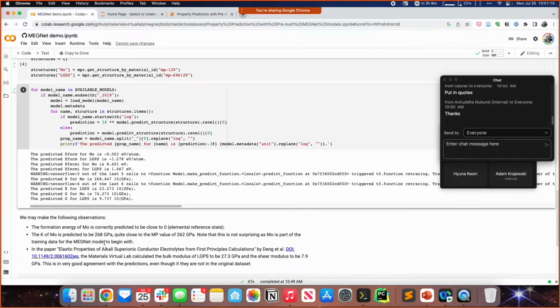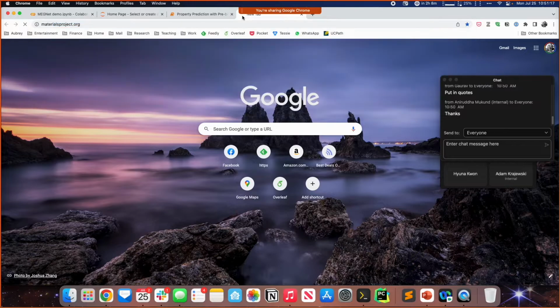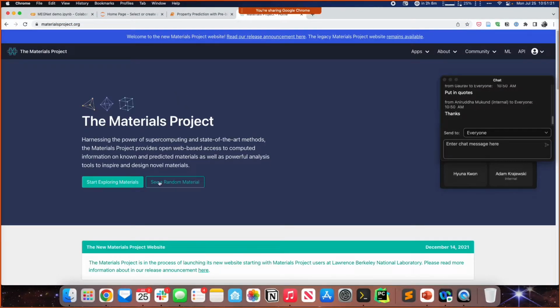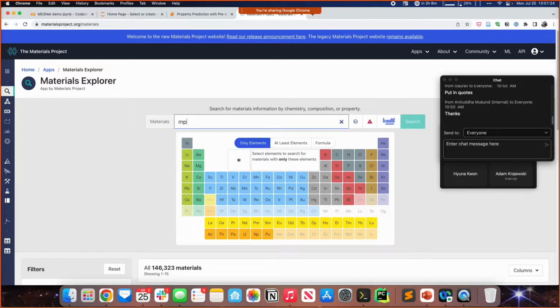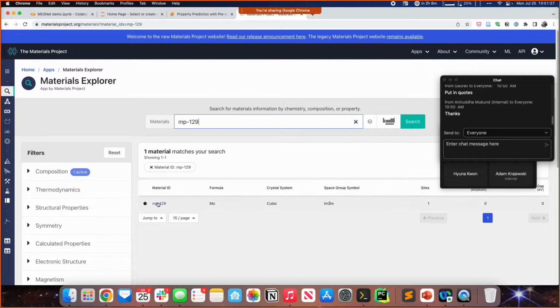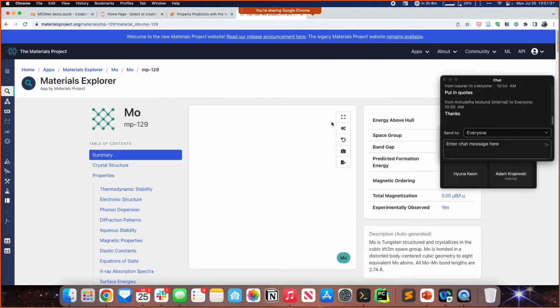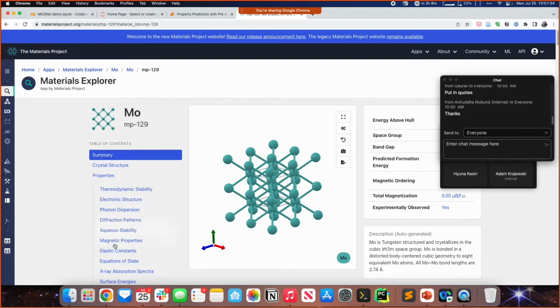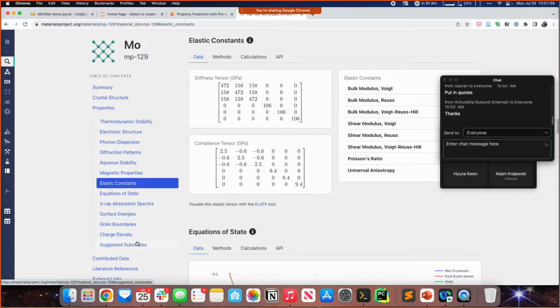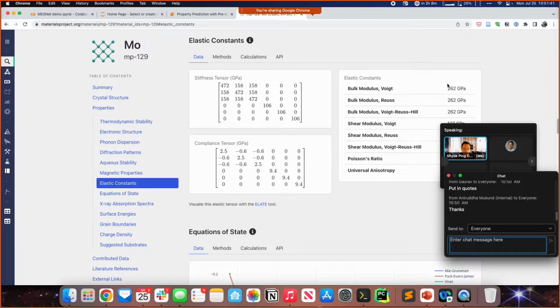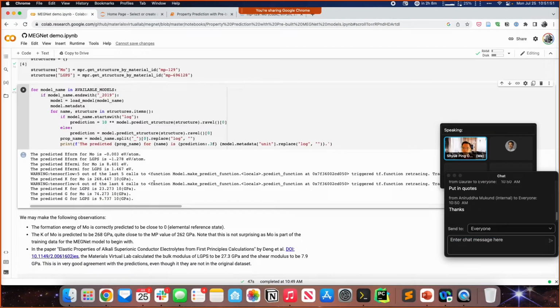So for moly, we can actually look at the materials project data, right? So let's say I go to materials project and I search the materials. If you look at the materials project, they have all this information over here, but one of the things you have is the DFT calculated elastic constants. And what you see here is that the calculated bulk modulus for molybdenum, BCC molybdenum, using DFT calculations is 262 gigapascal. And what we have here is 268 gigapascal, right? So as you can see, the model is pretty accurate, right?